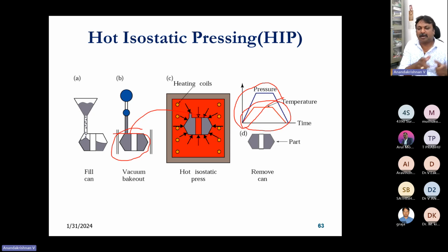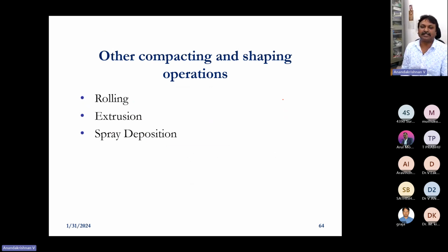So what they do is take the component, after it is removed from the base structure, and put it inside hot isostatic pressing. They do a HIP process, hot isostatic pressing. They will increase the pressure and temperature so that the component will become uniform, having homogeneous properties in all directions. Then only it can be used for high wear-resistant components or any kind of bearing materials.